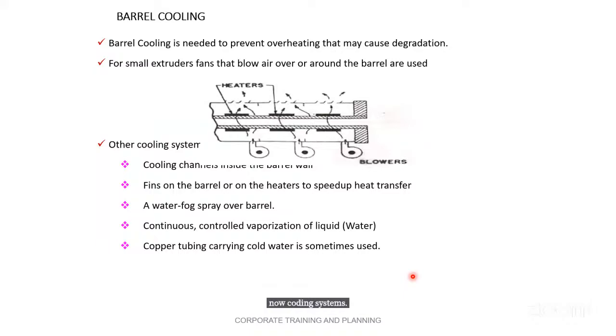I told you cooling is very essential for the extruder because heat is developed by the shearing heat. Barrel cooling is needed to prevent overheating that may cause degradation of material. For small extruders, fans blow air around the barrel. See, these are the blowers here. I told you, these are the heaters, these are the blowers, which will pass a cooling effect on the barrel and immediately control the temperature.